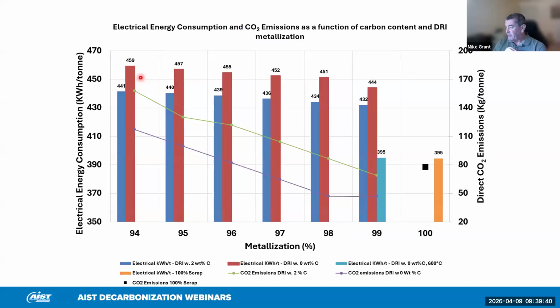And if we look at the different cases, comparing 0 carbon DRI with 2% carbon DRI, starting with low metallization all the way up to high metallization, you can see obviously that the higher the metallization, the lower the power consumption, or the higher the productivity of the electric arc furnace. Compare this with the 100% scrap case here.